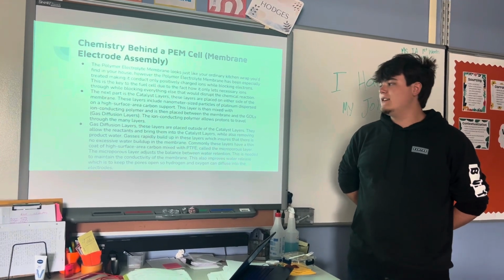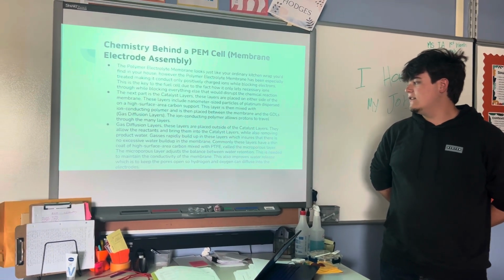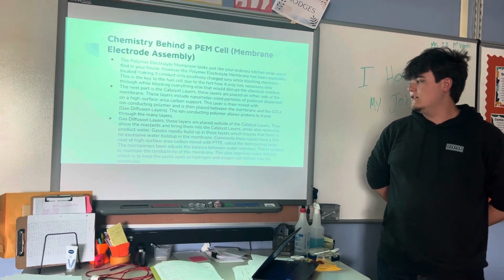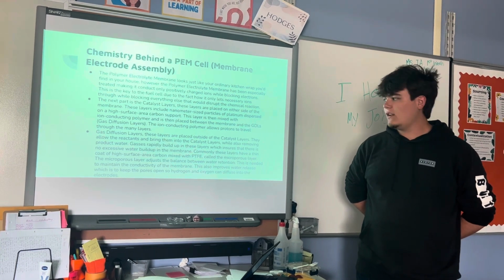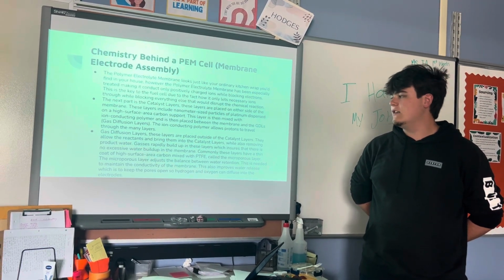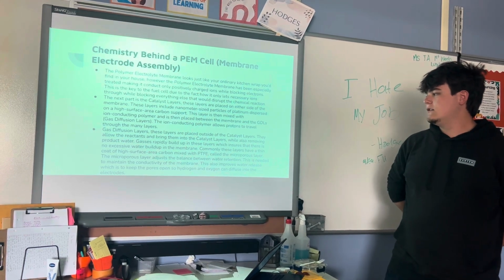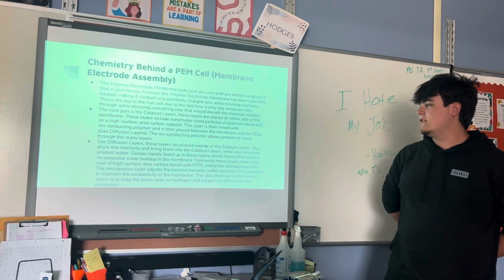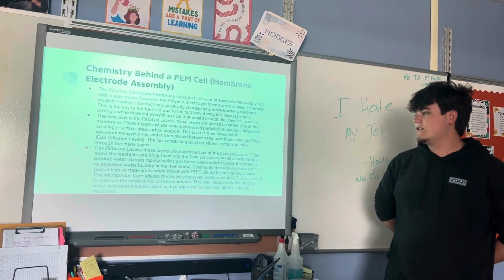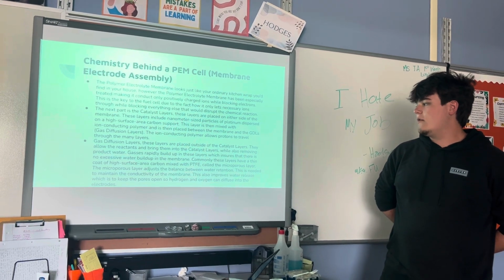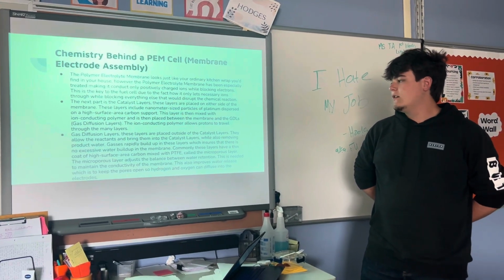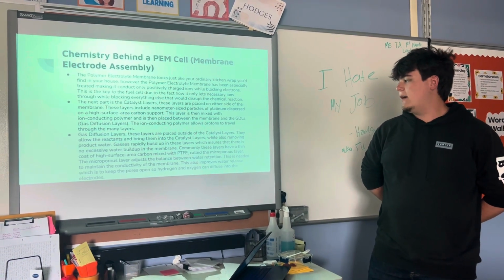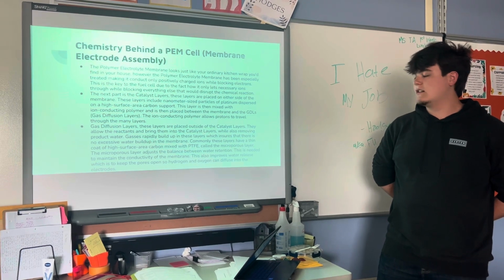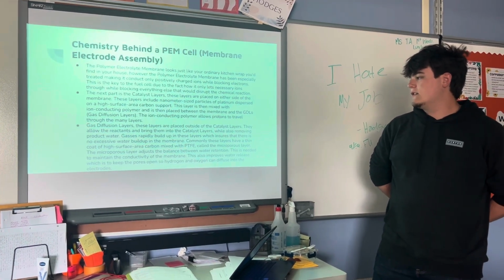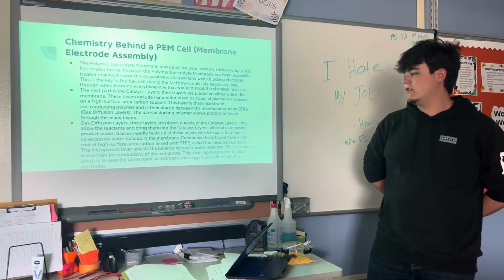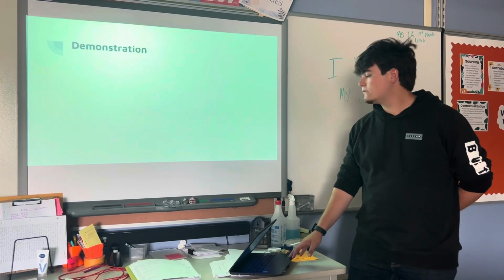The last part of this assembly is the gas diffusion layers. These layers are placed outside of the catalyst layers. They allow reactants to come into the catalyst layers, while also removing product water. This ensures that there is no excessive water buildup in the membrane. Commonly, these layers have a thin coat of high surface area carbon mixed with PTFE called the microporous layer. The microporous layer adjusts the balance of water retention. This is needed to maintain the conductivity of the membrane. This also improves water release, which is to keep the pores open so hydrogen and oxygen can diffuse into the electrolytes.